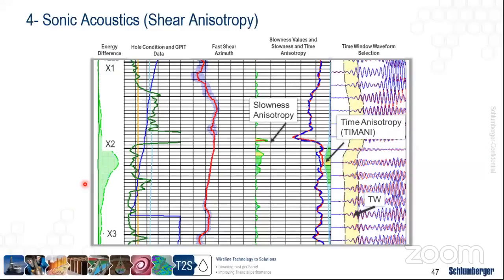So this is an output of the shear anisotropy. What typically happens is that we measure shear in two different directions. We measure it in the X and Y direction, which is shown here. The difference between the slowness from the X direction and the Y direction would show a separation. This separation also contributes to an energy difference between both waveforms coming back to the tool. Once we see there is a change in energy between the X and Y direction that's being shown here as a result of this separation, we can identify what we call a fast shear azimuth. Fast shear azimuth is the direction in which the fast shear, which is the fast shear slowness, is propagating.